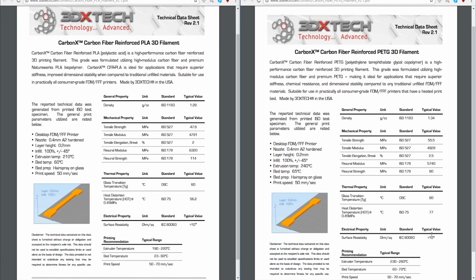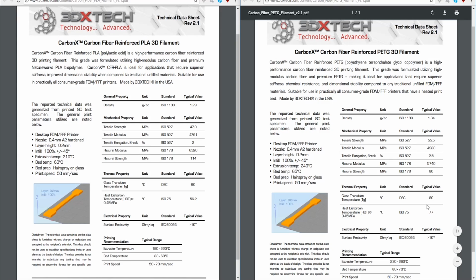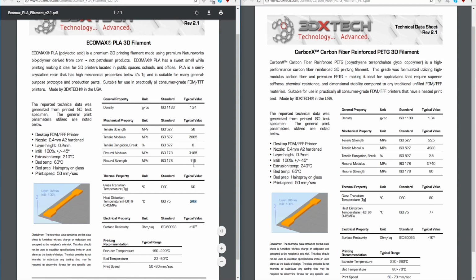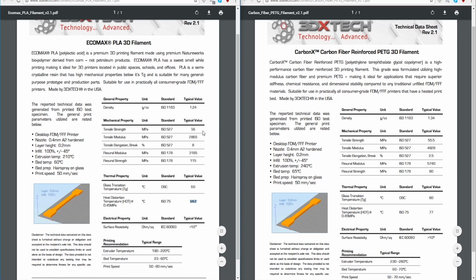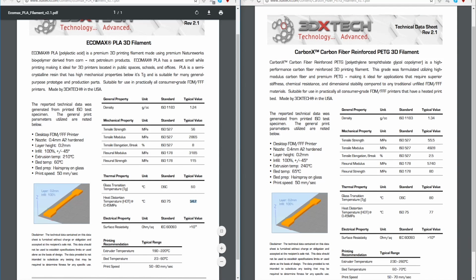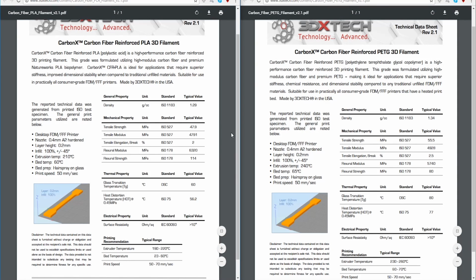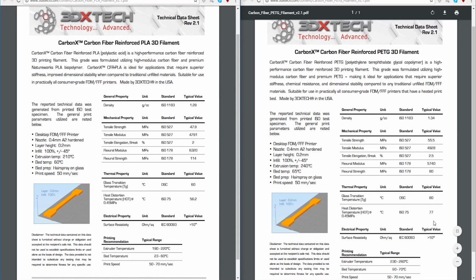I'm reading the little paragraph above. Yeah, so anyways, it almost beats out PLA. You get a little bit more flex, better temperature stability, better tensile strength, and the PETG is a little bit more dense than PLA, not much. Almost as much flex, but it seems like PLA is incredible under flex. And compared to, of course, like we said here, not nearly as high here, higher here. This is standard PLA, yeah. So just comparing, it's better temperature stability, but it needs a heated bed.